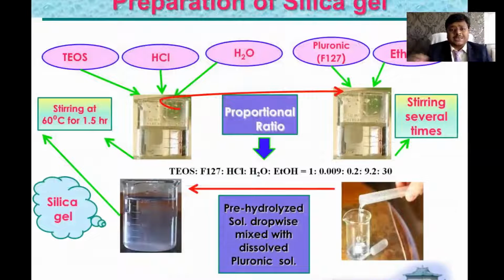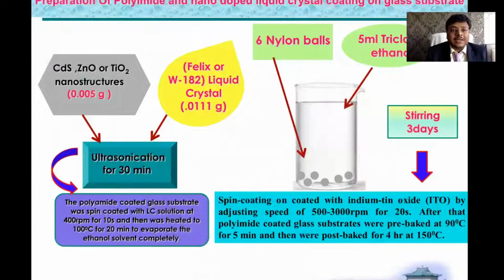We also prepare the silica gel from tetraethyl orthosilicate, HCl, H2O, pluronic, ethanol. We just make a ratio. In this ratio, we make a clear, transparent, pre-hydrolyzed solution dropwise. Why? It is for silica coating, for high reflection. Silica gel coating is required for high reflection. That's why we prepared this silica gel coating. And this is polymer coating. Why it is required, I will discuss.